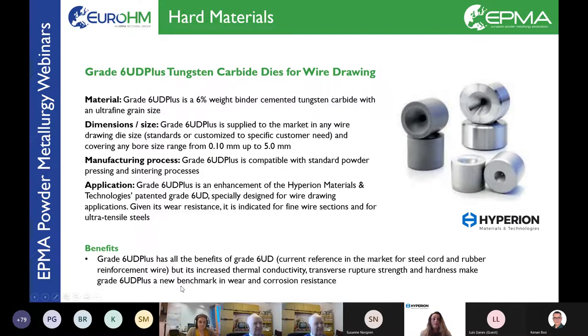To meet those requirements, Hyperion developed a proprietary cemented carbide grade, 6UD plus, for wet wire drawing of ultra-high tensile strength steels for tire core reinforcement. 6UD plus is characterized by a 6% weight binder content and ultra-fine grain size. The unique 6UD plus material design leads to a high hardness, up to 2050 Vickers hardness, as well as to increased thermal conductivity and corrosion resistance.